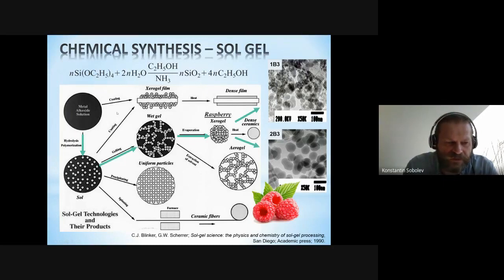As a result of this reaction, you have hydrolysis first, and then polymerization. So you form a sol, basically a dispersion of nanoparticles in alcohol and water. Removing the alcohol sometimes is challenging. Sometimes there are elegant solutions. But obviously, the path we usually use is to produce a wet gel, then evaporate the solvents and produce xerogel, and from xerogel, with a raspberry structure, to produce particles for concrete application.